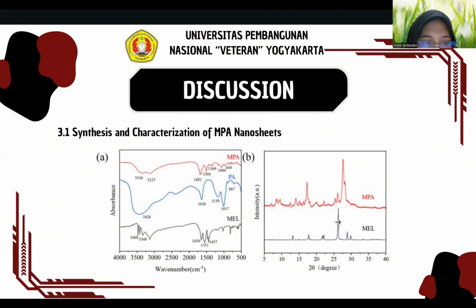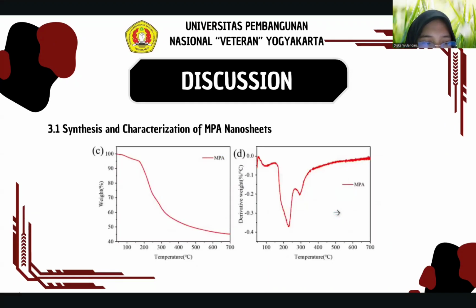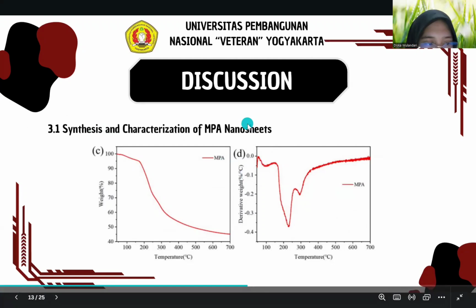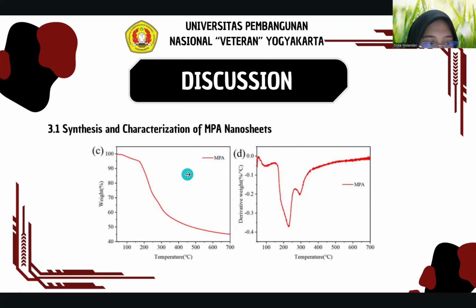Thermal stability shown in TG and DTG curves, figure 2C and D, indicated that MPA had good thermal stability with a 45% residue at 700. XPS spectra, figure 2E, confirmed the presence of phosphorus and nitrogen.